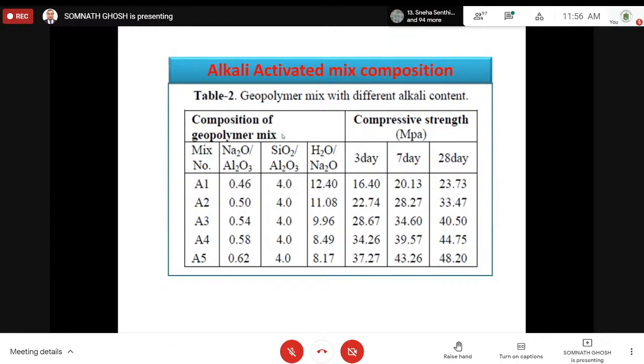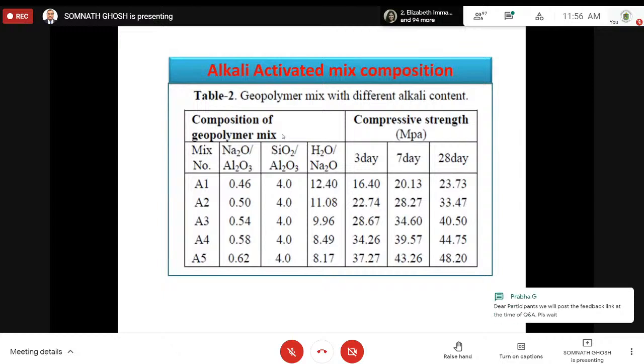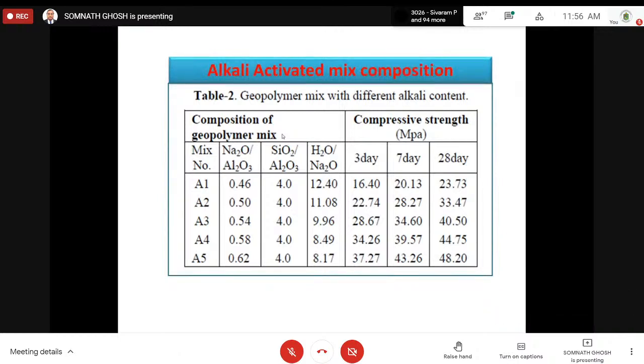It happened to me while publishing a paper in ASTM. I went for an NMR test, and through the NMR test, I found that there is no trace of polymeric reaction when blast furnace slag and alkali and silicate are reacting together. That's why you must be sure that there is polymeric reaction, and then you should tell people. So now I'm generally using the term alkali activated. Geopolymer, we can always use for fly ash because it is real geopolymer, polymeric.